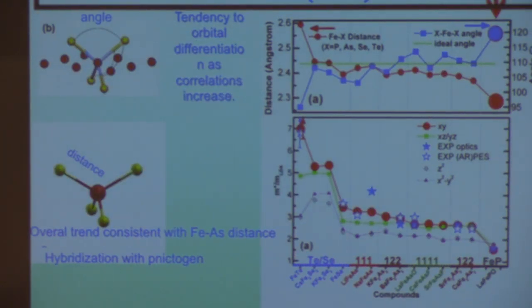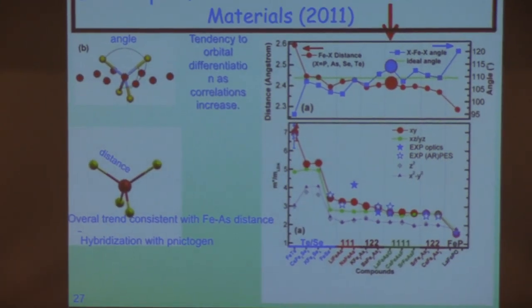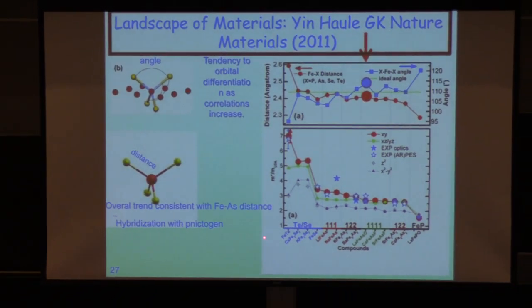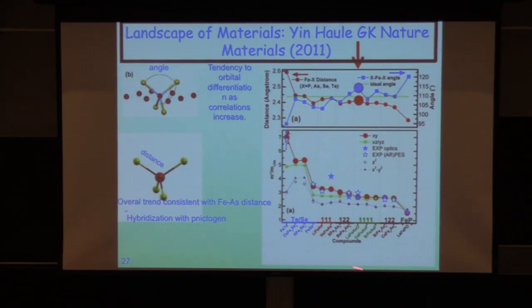The other thing we can do is, now we have lots of compounds, we can scan through them. And again, this only became feasible in the last year, that we can do calculations not for one compound, but for many, many of those. And we can try to see what governs the mass enhancement, what is the systematics, what's really important, and understand what sort of chemical handle allows us to vary them. The x-axis, in this case, is the pnictogen height. As we change the pnictogen height, we can get masses which are as small as 1 or as large as 7. The average is actually 3. Yes?